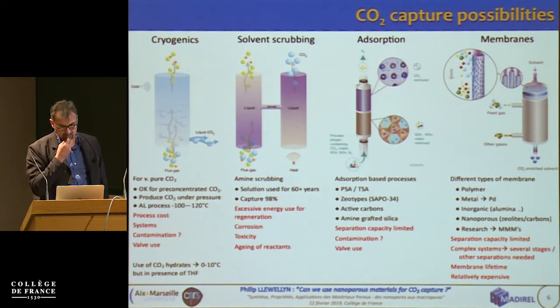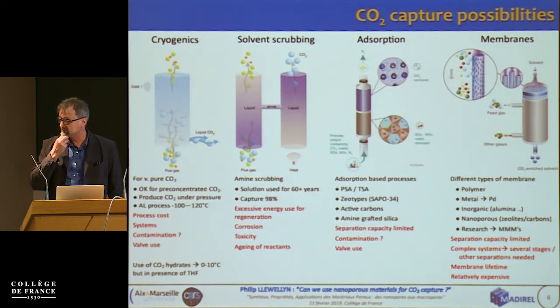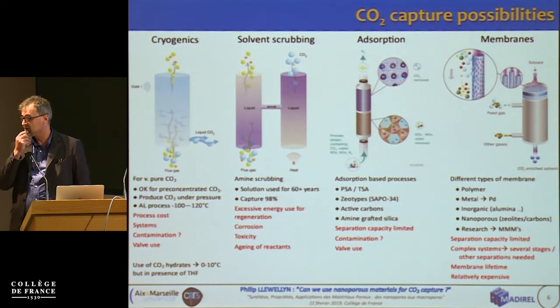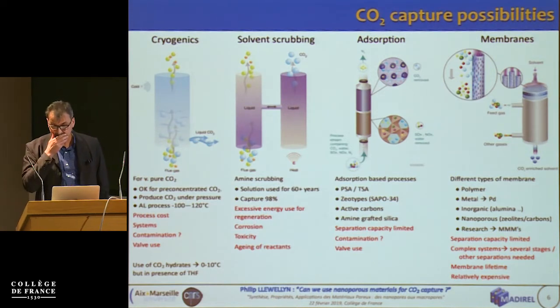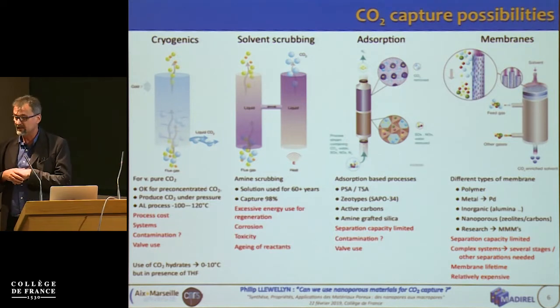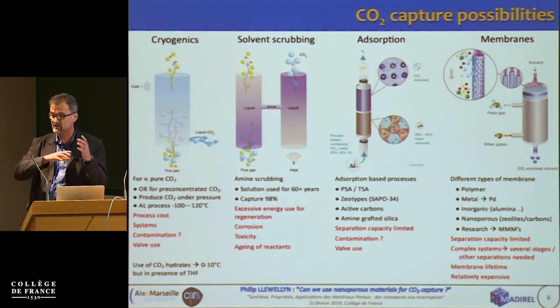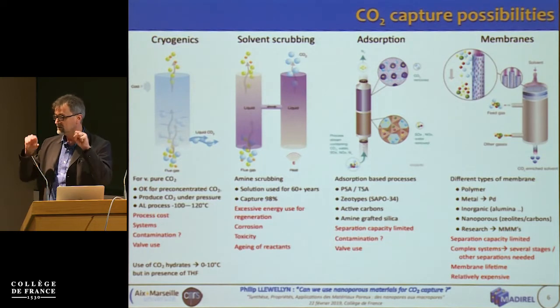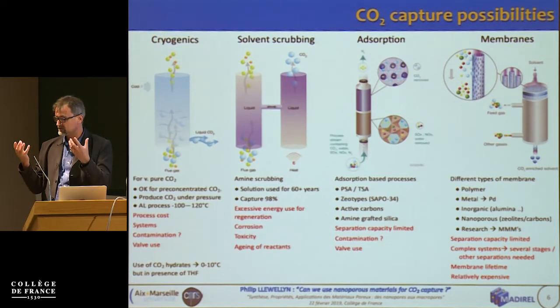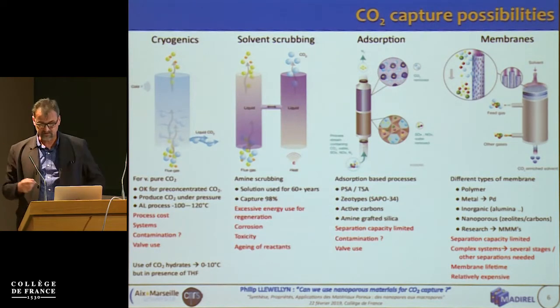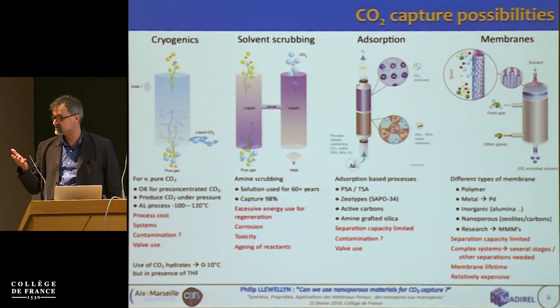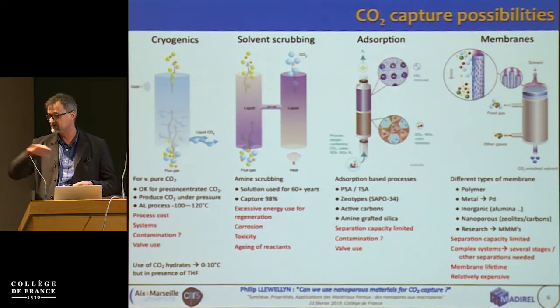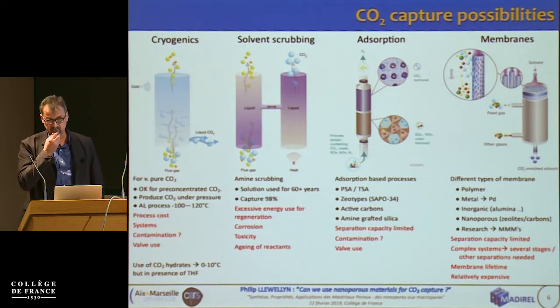The problem with adsorption at the moment is that sometimes we can have problems in terms of capacity. So we'd have to have materials with maybe better pore volume. Also the problem with contaminants. What happens if we have water in the system already? SOx, NOx, other things like this. And of course, depending on the type of process we're looking at, if we're playing around with pressure, and I'll come back to this, we have valves that open and close. So from a process design point of view, we also have a problem in terms of the aging of the valves in the process itself. Which is why a membrane system would be quite nice, because you just open the system up, the gas flows through, and we just pick off on one side the retentate that we're interested in.